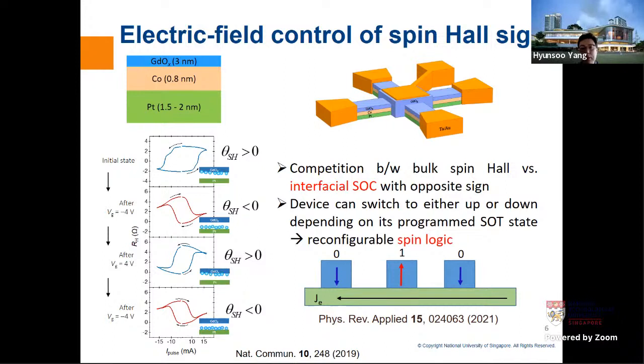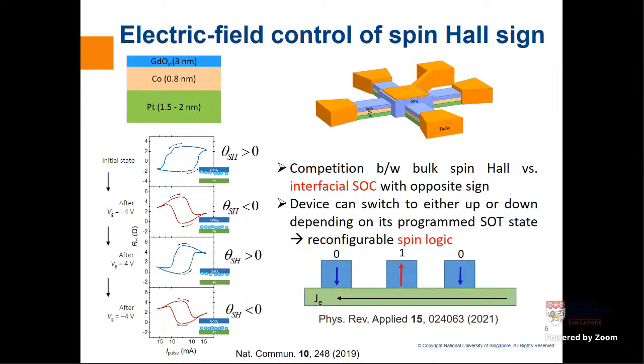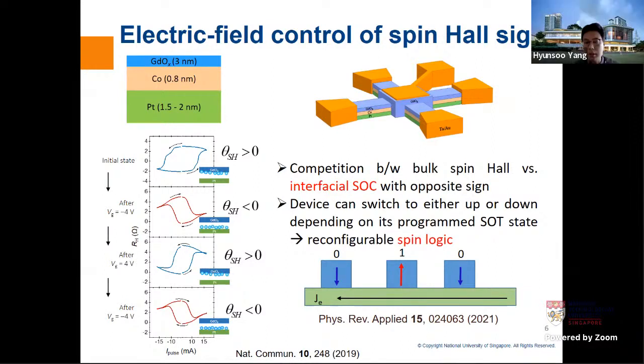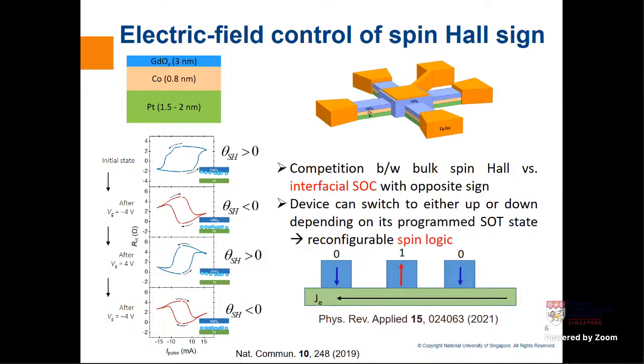Oh yeah, this is a very good question. Obviously, if you look at the detailed switching mechanism, everything is based on domain wall motion, unless you can make a single domain device. But if you want to make a single domain device, your device scale should be extremely small. For example, if you use perpendicular anisotropy material, you probably have to make it 20 nanometers or below. Just now you showed the results with a width of 400 nanometers. That's right, it's about 400 nanometers. So obviously, it's all due to domain propagation and domain-based switching. Yes, you are right. Okay.